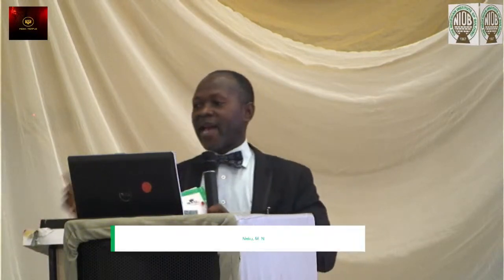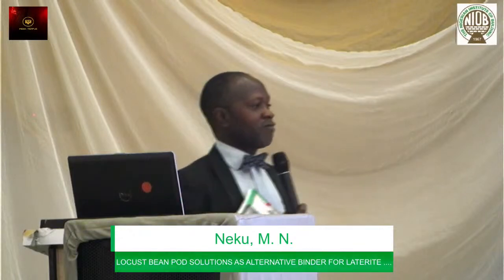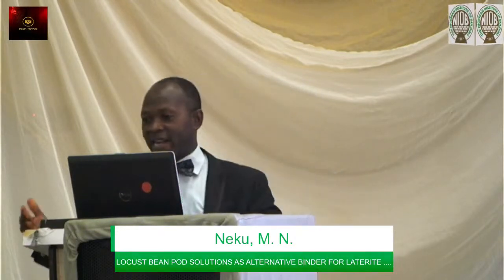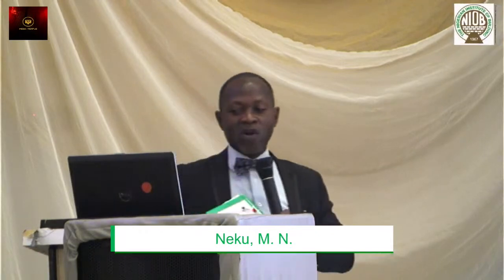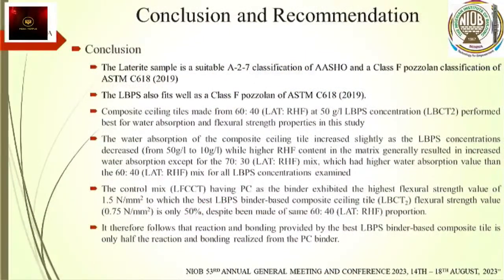But one unique thing was that the ultimate of the strength, which was 60-40, was also similar to the mix that we had for Portland cement. It was also 60-40. But the cement binder had a strength which is double the strength we had for the LBPS binder. And in conclusion, we had the following inferences. The laterite sample used is a suitable A2-7 classification of AASHTO and a class F pozzolana classification of ASTM C618.